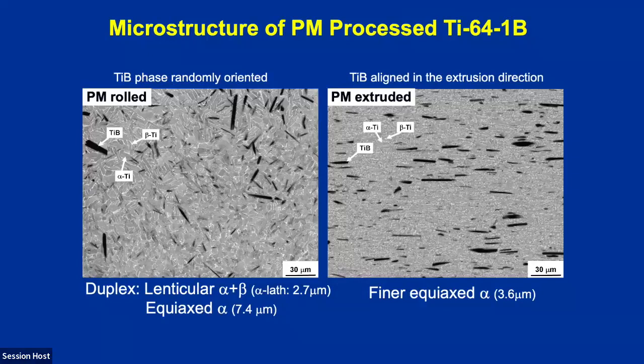In these backscattered images, the black is the titanium borides, as the boron tends to form TiB or TiB2. In this case, it's TiB. And they are significantly aligned with respect to the extrusion axis. But that wasn't the case in the rolled plate. And in addition, we can have texture within the matrix, which is the alpha beta matrix.